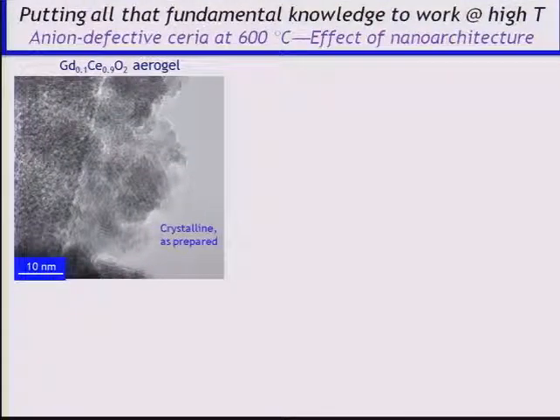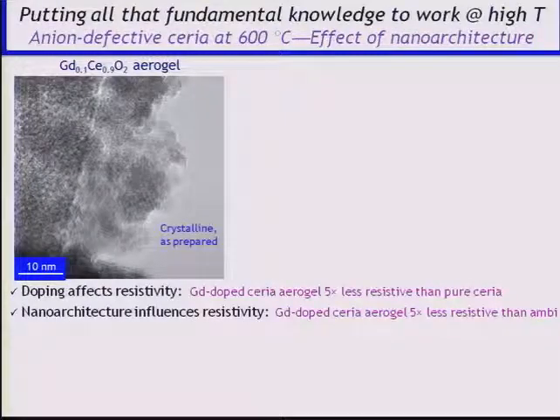But an oxide ion? Well, we made the gadolinium 3+ doped cerium 4 oxide aerogel, which would be of interest in a solid oxide fuel cell, which has to operate at 600 degrees C. We found that the gadolinium did what it should do, introduced anion vacancy, so it was much less resistive than the pure ceria aerogel. And we had an architectural difference now. The aerogel was much less resistive than the ambigel.